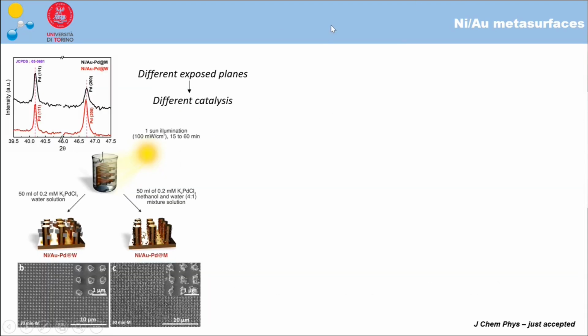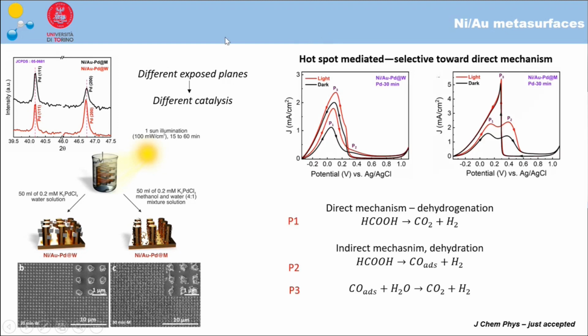Another example of fuel cell, in this case, we create a different metasurface. We use a nickel gold metasurface where we deposit palladium particles in two different ways using two different solutions, and we create basically two different nanoparticles deposited selectively on the pillars or not selectively over all the surface. And in this case, we use fuel cells based on formic acid, basically oxidizing formic acid. We can basically generate hydrogen, and also, of course, drive the oxidation reaction in the fuel cell.